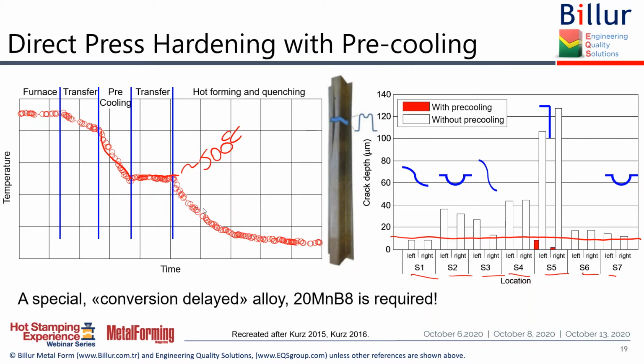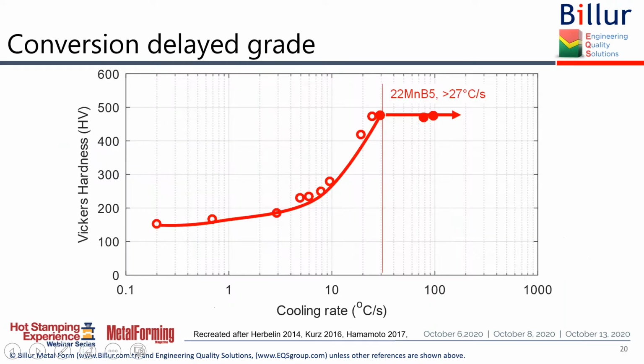But for this, we need a special so-called conversion delayed alloy, and it's called 20 MnB8. This is developed by voestalpine. I have the references down there. So what do we mean by conversion delayed grade? Remember we talked about critical cooling rate for the typical steel, 22 MnB5 as 27 Celsius per second.